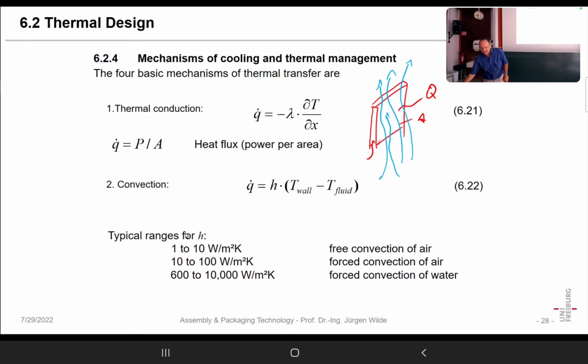Okay, then we have forced convection. So maybe the heat transfer coefficient can go up to 100 watt per square meter and Kelvin. But what is much better is, of course, water cooling. And here values between, let's say, 600 and 10,000 are typical, but these are defined mainly by the characteristics of the flow. So for instance, it depends much on the Reynolds number of the flow we have here.